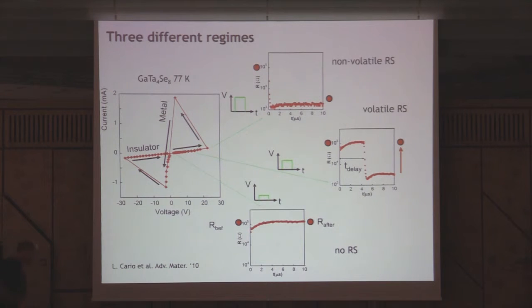Now, one problem that is in there is that this state, we do not have a lot of control how to undo this. So if you apply the negative voltage pulse, you sort of go back to a high resistance state, but not quite the same value. And sometimes you can do that with positive voltage, sometimes with negative voltage. So this thing is not totally, of course, the situation is reproducible, but not point by point.